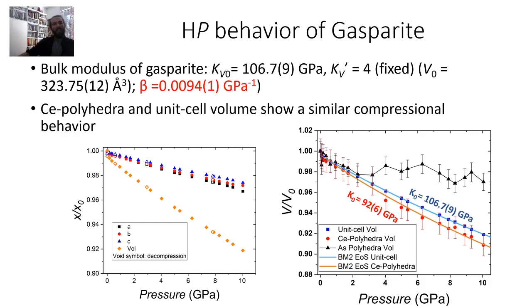Regarding the high pressure behavior of gasparite, the diagram on the left shows the evolution of cell parameters with pressure. In the pressure range under study, no phase transition has been observed, and the elastic behavior is slightly anisotropic, with a relatively higher compressibility along the direction parallel to the a crystallographic axis. A Birch-Murnaghan equation of state, truncated to the second order, was fitted to the experimental PV data, yielding a bulk modulus at ambient conditions of 106 gigapascal.